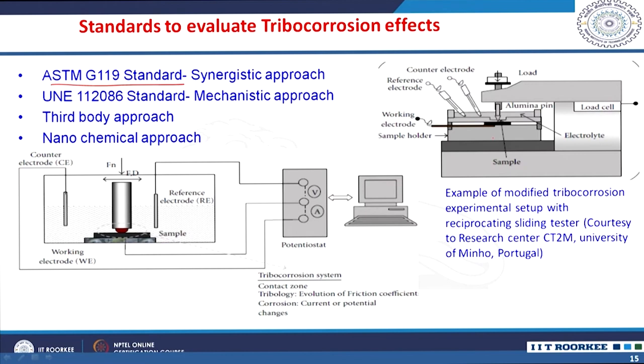So, these are all experimental approaches modified to evaluate the tribocorrosion wear, right. This is one reciprocating setup; when the load is applied, you can see there is a reference electrode and a counter electrode. This is the specimen sample, which is called the working electrode. So, in a corrosive environment under loading conditions and reciprocating movement, you can actually evaluate the effect of this sliding in a corrosive environment, the synergetic effects of mechanical wear and corrosive wear, that is tribocorrosion. There are certain standards available to evaluate the tribocorrosion effects.